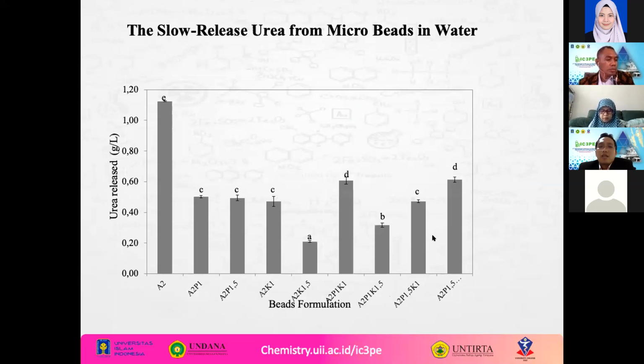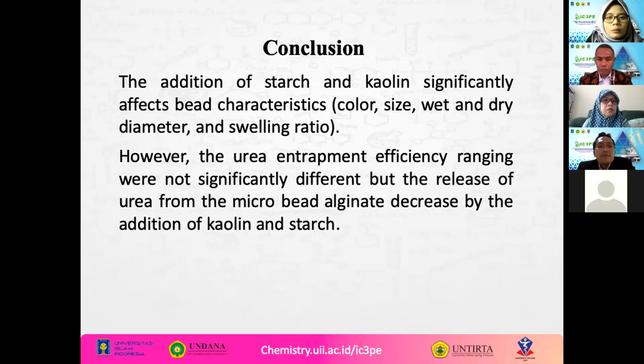But the slow release of urea from the microbeads in water is relatively different when we add starch or kaolin. The addition of starch and kaolin can decrease the urea release in water over 24 hours. This is the data. And the best composition for the smallest release of urea is when we add kaolin at 1.5%. And the conclusion: the addition of starch and kaolin significantly affects bead characteristics. However, the urea entrapment efficiencies were not significantly different, but the release of urea from the alginate microbeads decreased with the addition of kaolin and starch.